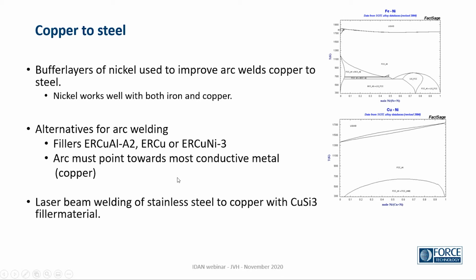There have been developed other filler materials, especially for this combination, like the copper aluminium or copper nickel filler materials, which could be used. And of course, we talked about the heat conduction from copper, so we need to point the arc against the most conductive metal, which in this combination is the copper. And laser welding with copper silicon filler has also been attempted.